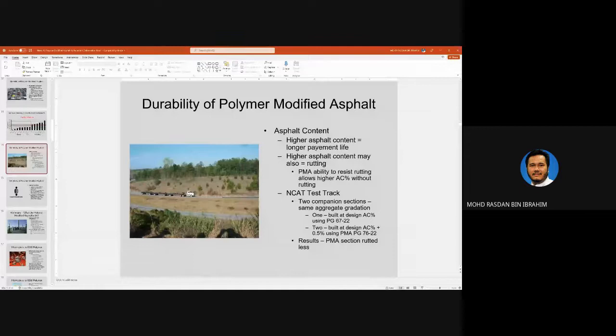But if it is too much, then it can cause rutting, meaning that the surface of the pavement where the tires of the vehicles pass will have a deflection. So that is rutting. So PMA is able to resist rutting and allows higher asphalt content without rutting. This is a trade-off. You'll be able to use a higher amount of bitumen, but if it is still too much, it doesn't matter if it is polymer modified or non-polymer modified, if it is too much asphalt, too much bitumen, the rutting will occur. So this is this test track here.